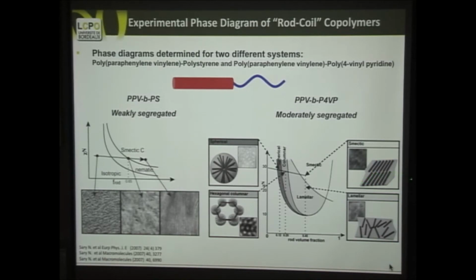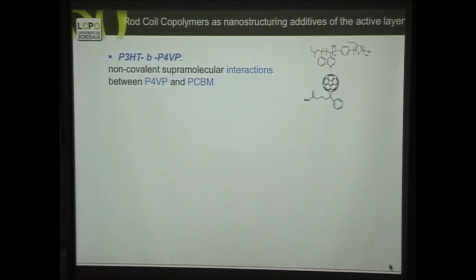If here you can go by hopping very easily, but here, if the mean free path of the hopping of the charge is less than the randomness of this kind of disorder of the cylinders there, then you will not have good transport. You see, now we have a good tool to play with the chemistry and make the right materials. So, just to reach the end of the talk, we made a block polymer of polythiophene and poly-4-vinyl pyridine, which has 2 electrons that can complex and have weak supramolecular interactions with the C60, so that we can make the donor phase and the acceptor phase by freeing up and having the organization of that.